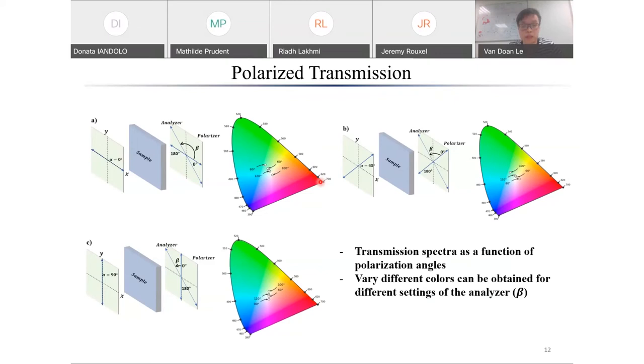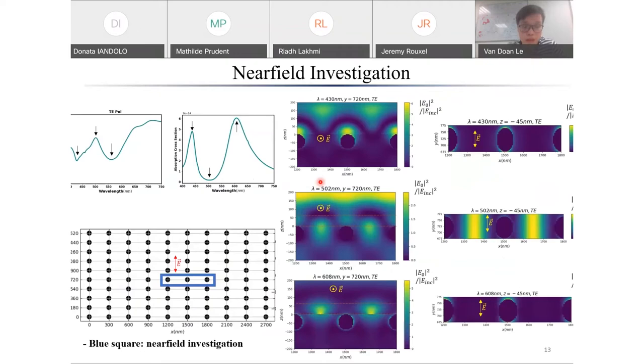To understand the origin of the phase variation of the sample, I show you the near field investigation. I mentioned previously that there are three points we want to investigate: the dip in the transmission, the peak, and another dip. These can be related to the peaks and dips of the absorption cross section. It may not be at exactly the same wavelength because our sample is scattering, so the transmission takes into account the loss due to scattering, but the physical mechanism still holds around that point.